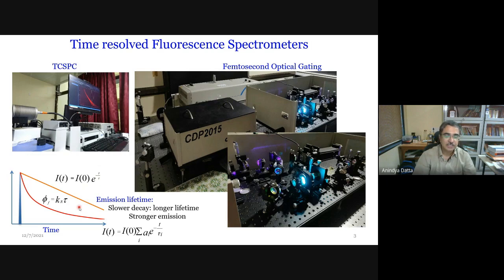Lifetime, once again, for single exponential decays, is actually a measure of how brightly fluorescent or how brightly photoluminescent our sample is. The relationship between emission quantum yield phi f and the lifetime tau is simple. The proportionality constant is the radiative rate constant. Similarly, if we write 1 minus phi f on the left hand side, the constant is going to be k_NR, the non-radiative rate constant. The excited state can decay by radiative as well as non-radiative pathways characterized by their own particular rate constants. So this is how, by recording spectra, determining fluorescence or photoluminescence quantum yield and recording lifetimes, we can actually get an idea of the rate constants of the radiative and non-radiative processes that are involved.